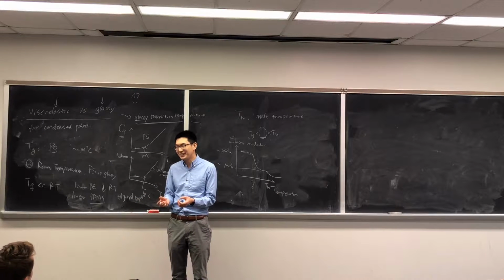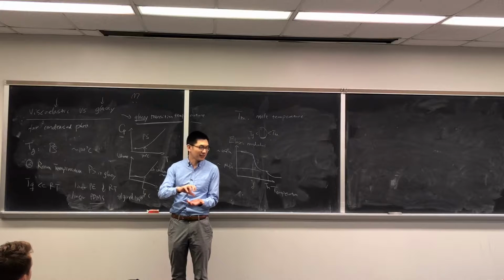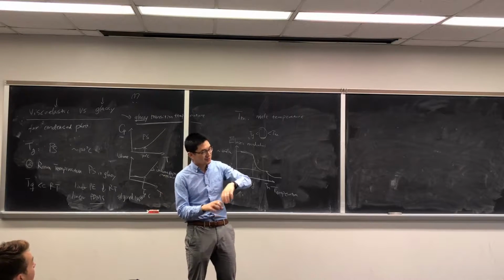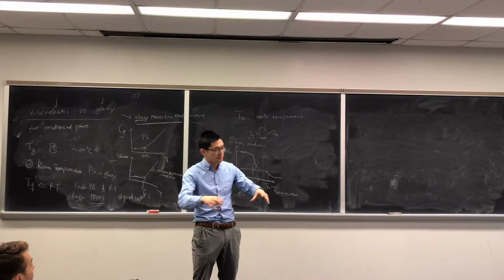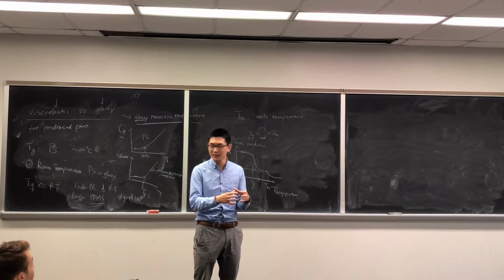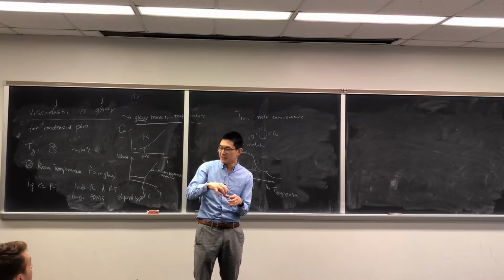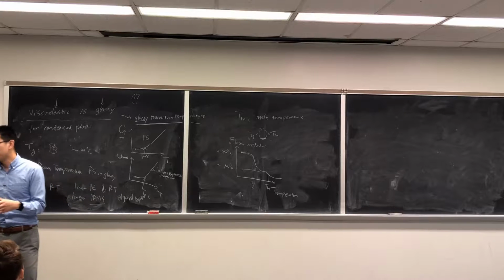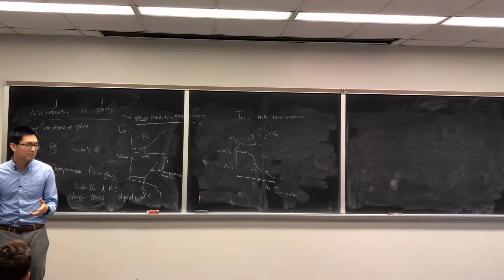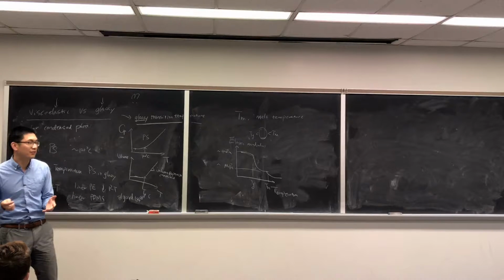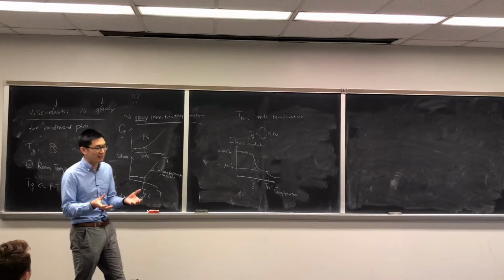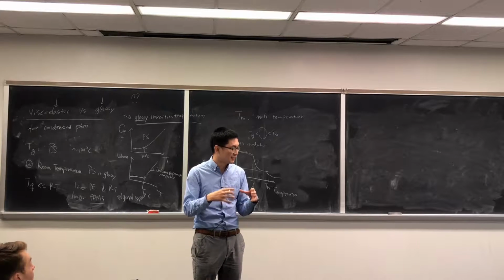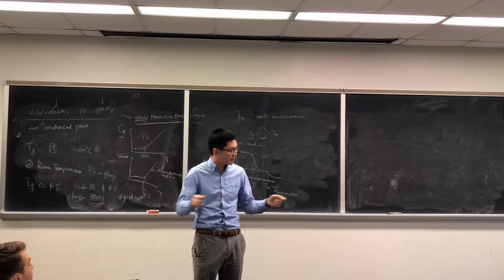So what you get is a liquid-like material. I wish I could show you. If you pour honey into a beaker, that's typically what high molecular weight PDMS is like. And you need to add a little bit of catalyst, which is a cross-linking catalyst. You stir them, leave it at room temperature overnight or put it in an oven for about 2-3 hours. Then you get a transparent disc, okay? And this is very stretchy and elastic.